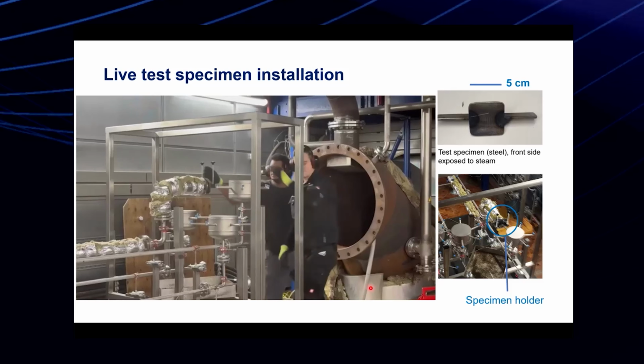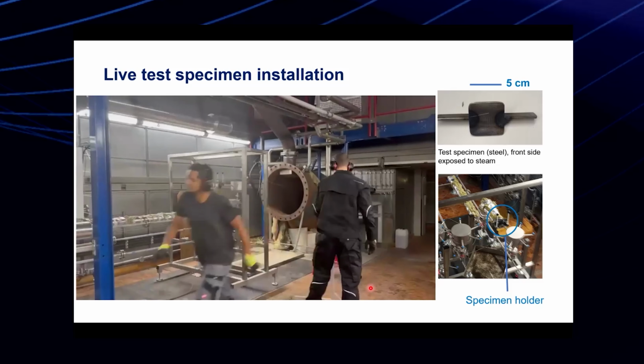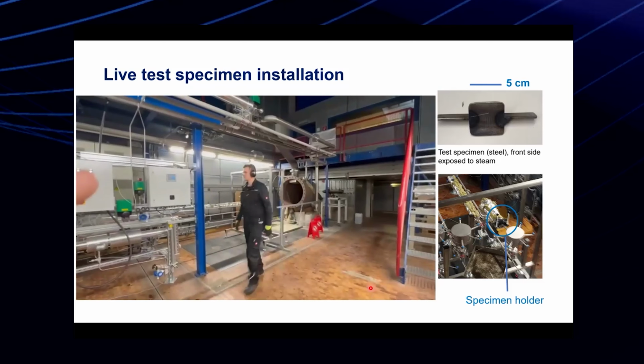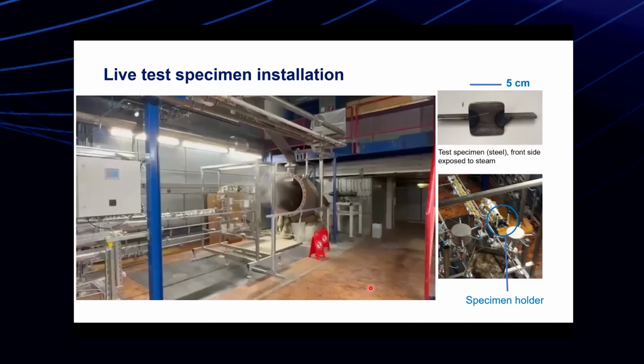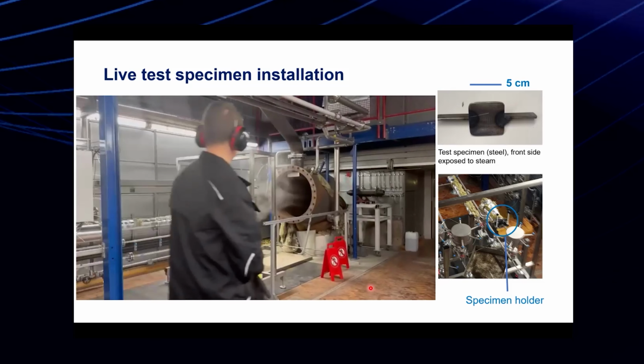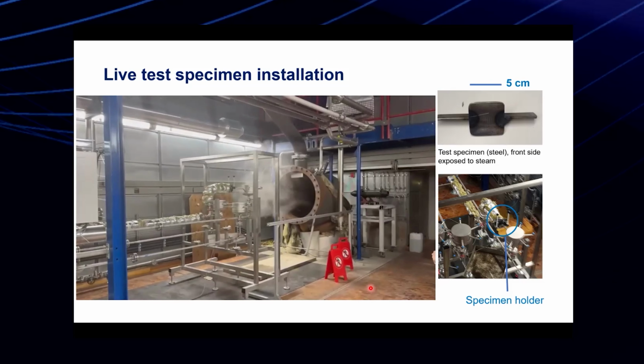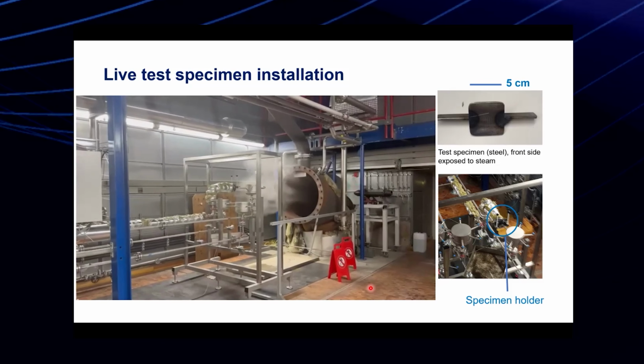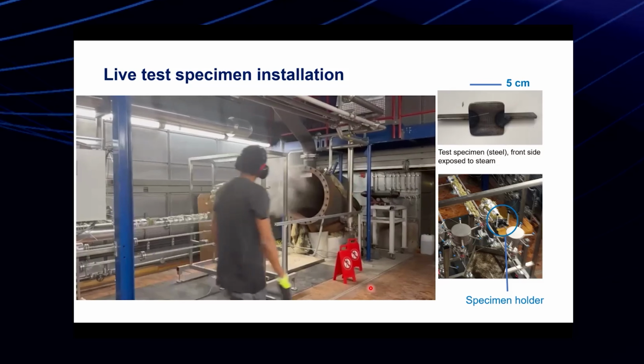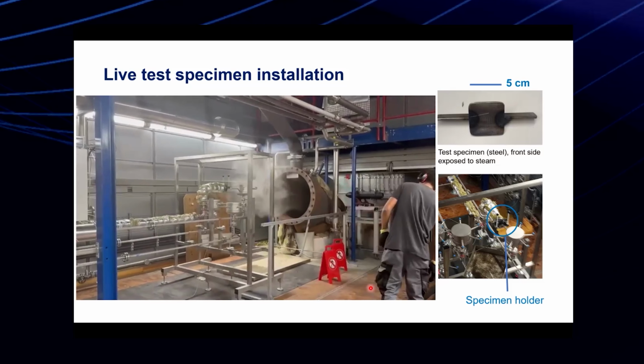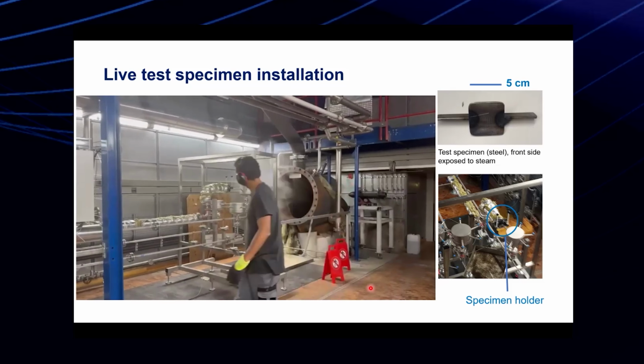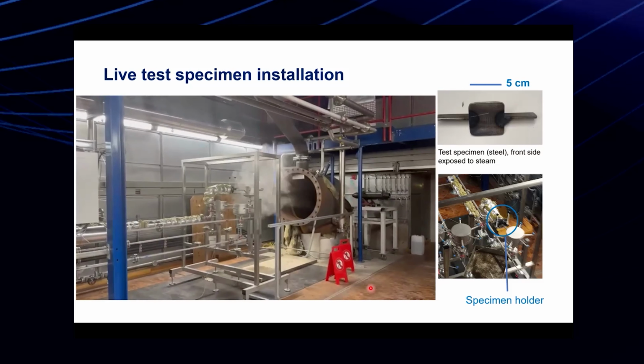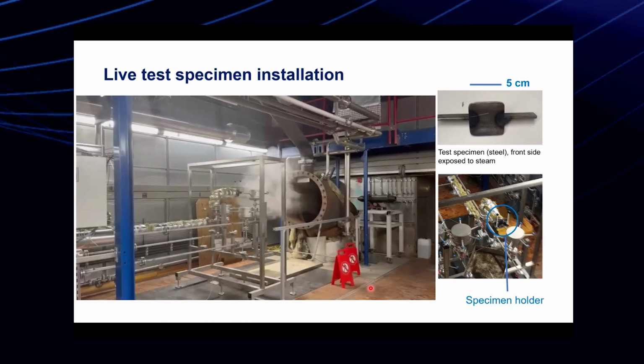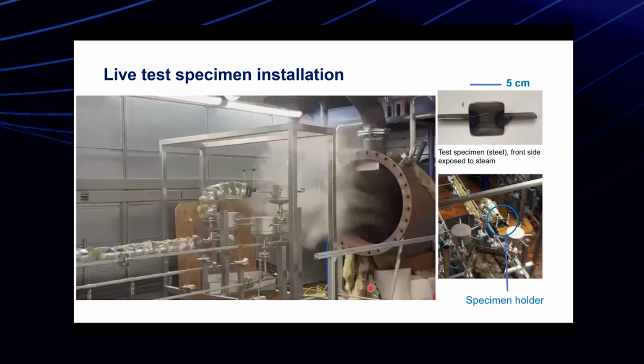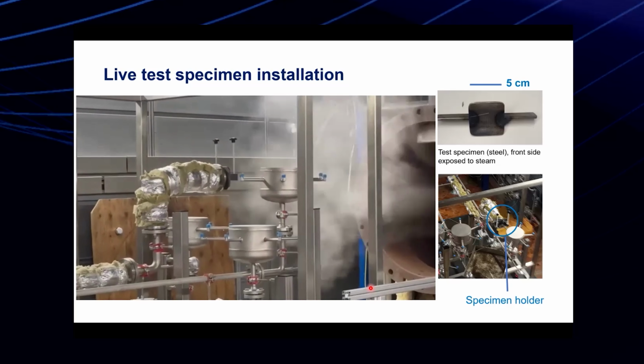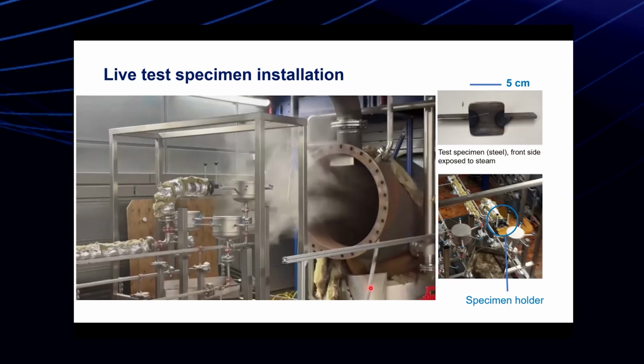As you can see, once they put the specimen in place, the steam is live steam, and this is where the steam starts immediately. This is your superheated steam. We want to make sure that there is absorption on this metal surface. Of course, there will be some limitation because the boiler is only operating a maximum of 8 hours, but at least we want to see whether we could see any absorption on the metal plates.